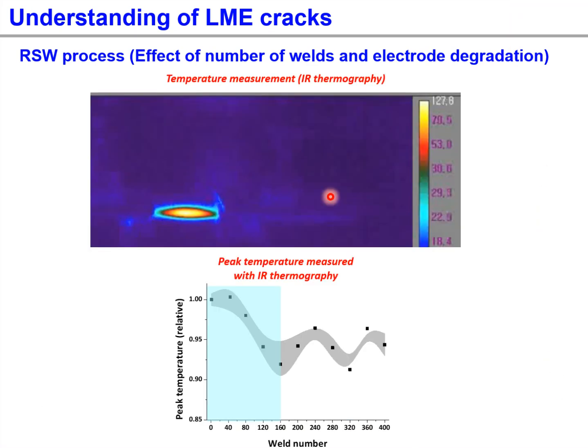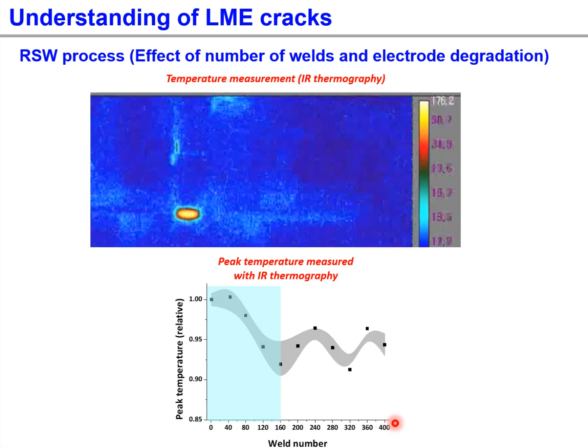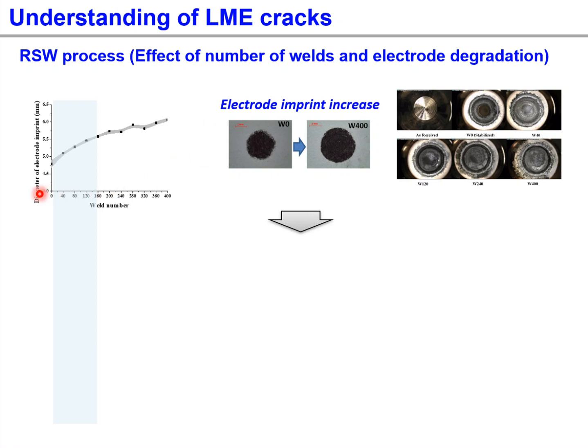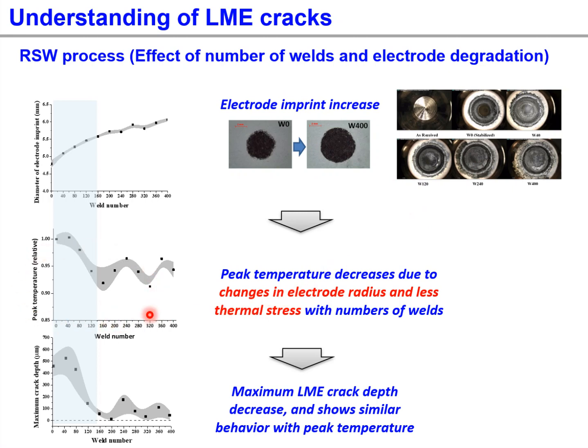Since the surface temperature is known to be directly related to LME cracking behavior, peak temperature was measured with IR thermography and recorded at each weld. The surface peak temperature also shows a large drop until 160 welds and remains at a low level until 400 welds. With an increasing number of welds, the diameter of the electrode imprints increases, which is due to changes in the geometry of the electrode surface. Also, surface peak temperature decreases dramatically up to 160 welds